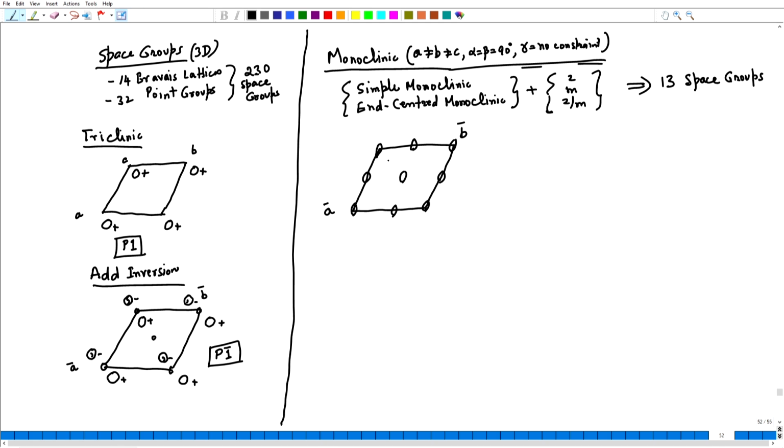If I put a motif here above the AB plane, the two-fold will rotate by 180 degrees, bring it here, and then the translations will take these two at all the corners. So, you can see that if I consider this one out here and this one out here, this two-fold takes them on top of each other. Similarly, between this one and this one, this two-fold will bring them into self coincidence.